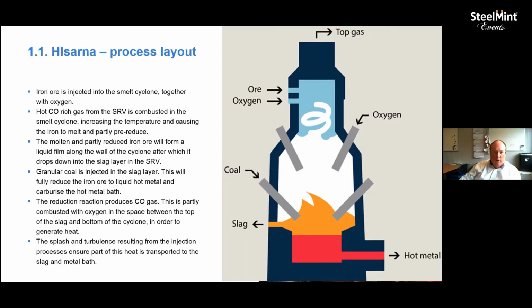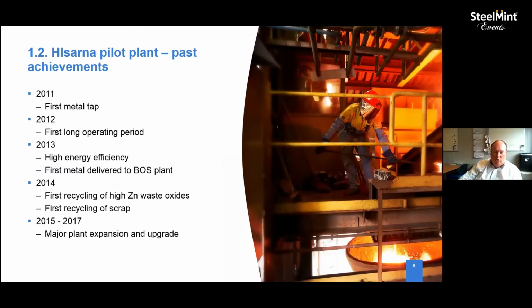Okay, then the things we have achieved so far. So in 2011, the plant was first started up, and that's when we did the first metal tap. And in 2012, we did the second campaign. That's where we demonstrated that we could actually operate the plant for longer periods of time, like up to a day and a half. Then in 2013 and 14, we managed to run runs of about 3 days continuously, and we demonstrated the energy efficiency that was originally calculated. We also supplied the first hot metal to the steel plant at that time.